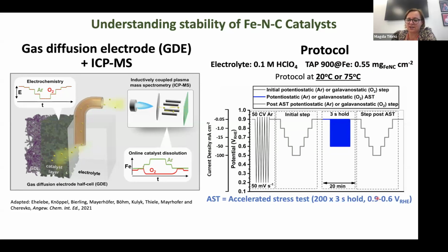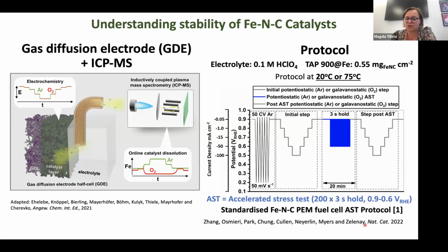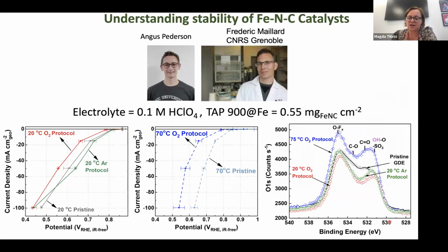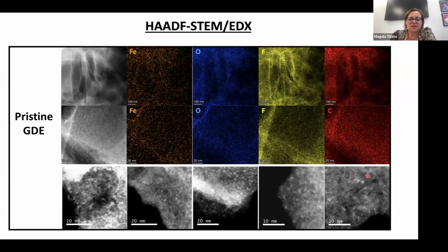We did this accelerated stress test, and if you want some more details about this, there's a very good paper from Zelenay in Nature Catalysis. Not to mention that, yes, the catalyst degrades. So once you do this accelerated stress test in oxygen at 20 degrees, you see how it goes down, and in particular at 70 degrees. And that's also because the surface of your carbon oxidizes quite a lot under these conditions. And so we looked, you know, at the pristine catalyst where you have the nice single sites.